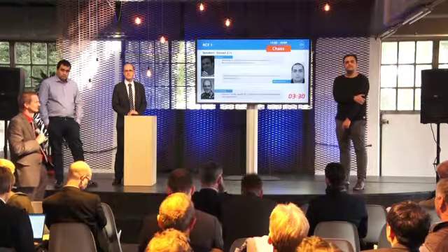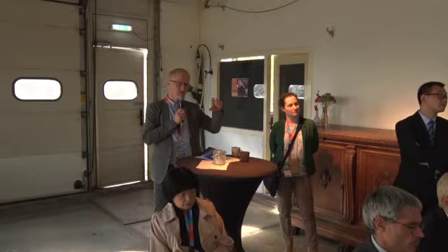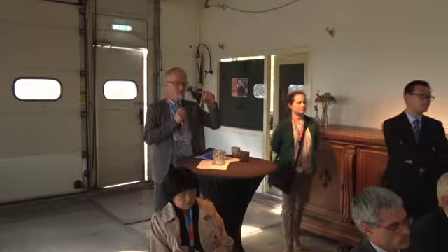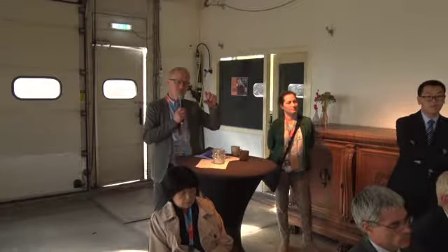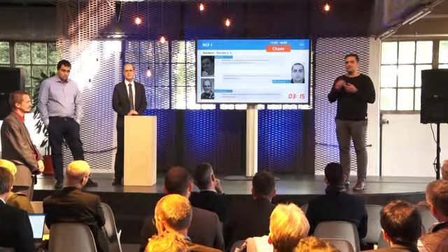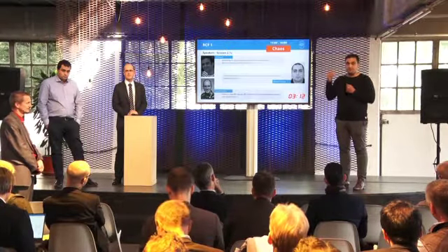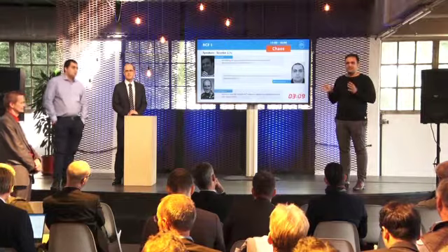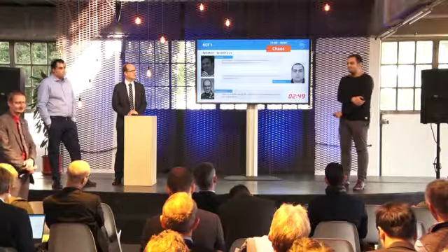In one of your pictures, we saw two layers of martensite, or one layer was tempered. Yes. And that was where the cracks were. As I explained in the presentation, we have the martensite layer. The volume of the martensite layer is larger than the base material, and the tempered martensite volume is more or less similar to the base material. That's the reason that we have compressive residual stresses in the martensite layer, and right below that, in the tempered martensite layer, we have tensile stresses. And that stimulates the crack initiation. Okay, thank you.